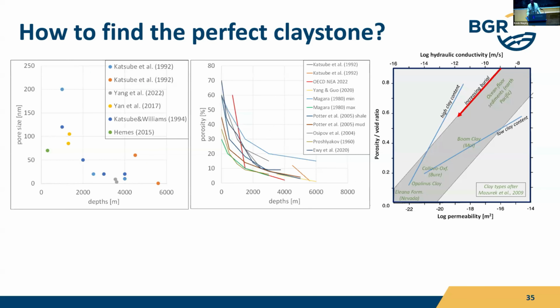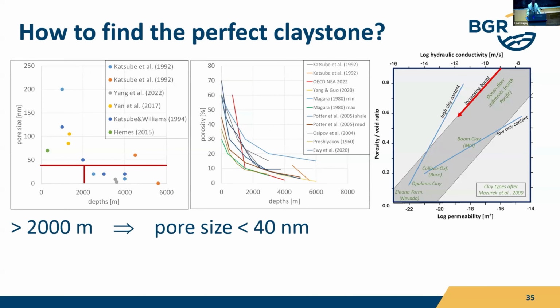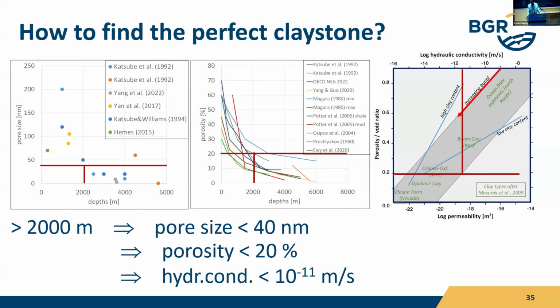These were the graphs I showed before. So if you look at them, we can fix them at a burial depth of 2,000 meters, for example, then the pore size on average would be below 40 nanometer. Porosity would be below 20 percent, and that would translate into a hydraulic conductivity of less than 10 to the minus 11, even for low clay samples, right? For a high clay sample, it would be much higher or lower hydraulic conductivity.